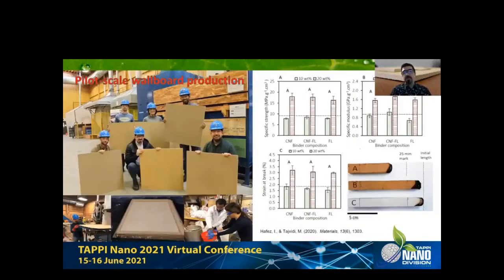This idea of enabling technology of contact dewatering also forced us to get into other products. This is a pilot scale production of wallboard or gypsum board. Gypsum boards are very common in North America, but these gypsum board replacements basically do not have any gypsum in them. They have that particle board in the core and the paper lining on both sides. This line shows the mechanical properties of the gypsum board, and we can get much better than that at a lower density. We are still working on the fire resistance, but initial test results have been promising. This is the one that we have developed, and this is the regular gypsum board.